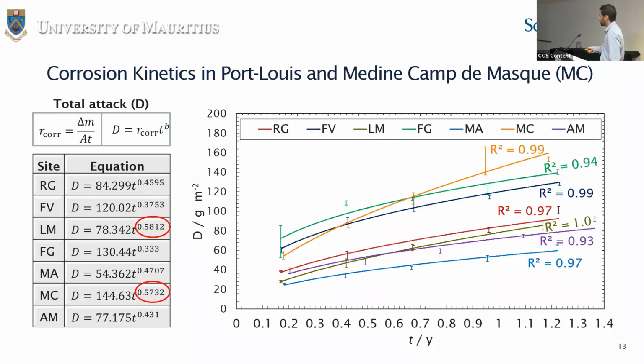The power law equations for all the sites are listed here, and there are two sites having a B value greater than 0.5, which implies that the rust layer on these two sites has low protection against corrosion.